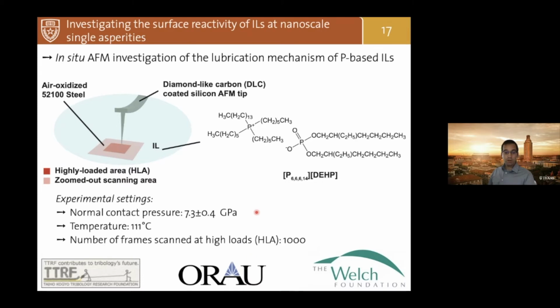The test that I'm going to talk about, again, is in the case of phosphonium phosphate ionic liquid, which is a well-known ionic liquid pioneered by researchers at Oak Ridge. We basically perform very high pressure tests, the highest we can go with AFM, in this dark red region. And every now and then we zoom out and we visualize what happens in this small area down here.